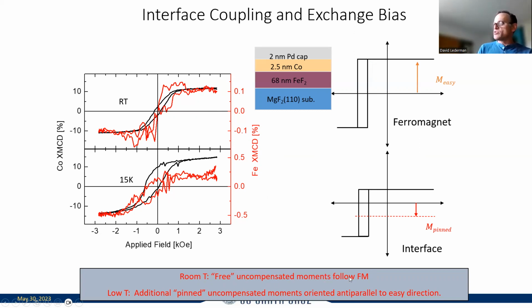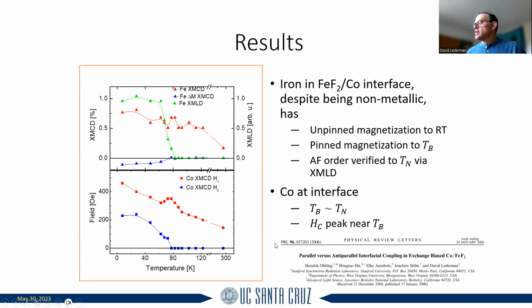So at room temperature, we have free uncompensated moments that follow the ferromagnet, and at low temperatures, we have additional pinned uncompensated moments oriented anti-parallel to the easy direction. Okay, and that's because it's shifted downwards, negative. Okay. So this is kind of an interesting